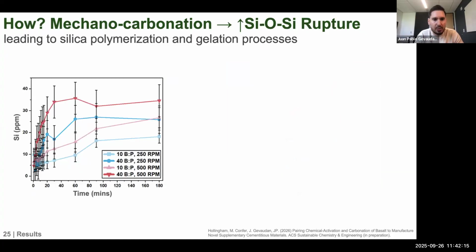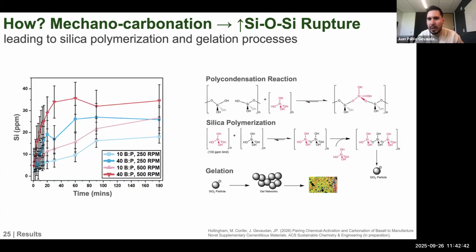Now, because our technology is operating at ambient temperature and pressure, we're actually able to look at the in situ dissolution reactions that are happening. And what we can see is that in the initial first hour of this process, we are rupturing that silicon-oxygen-silicon bond and releasing silica into the solution. Now, orthosilicic acid, which is highlighted here in pink, is not very stable and is going to polymerize through a polycondensation reaction, which I show here at the top.